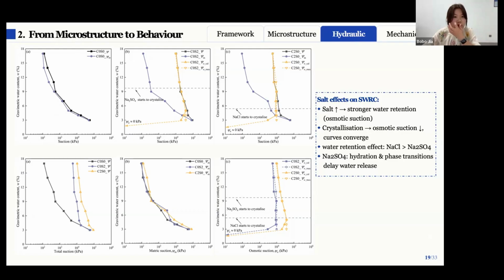And if we compare the two salts at the same concentration, sodium chloride shows a stronger effect on water retention than sodium sulfate. This difference can be explained because sodium sulfate solutions have a lower effective ionic concentration, and sodium sulfate exhibits a stronger hydration effect. It will influence how water is retained in the system.